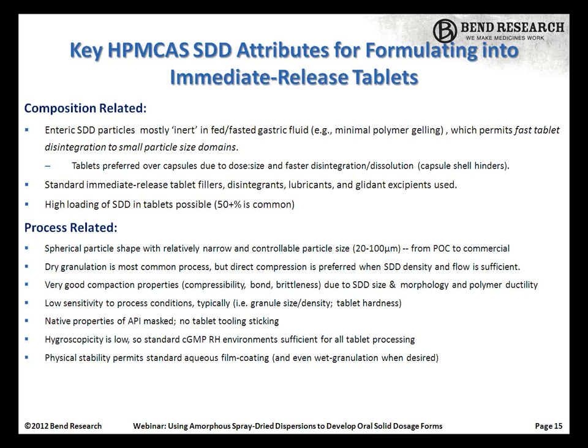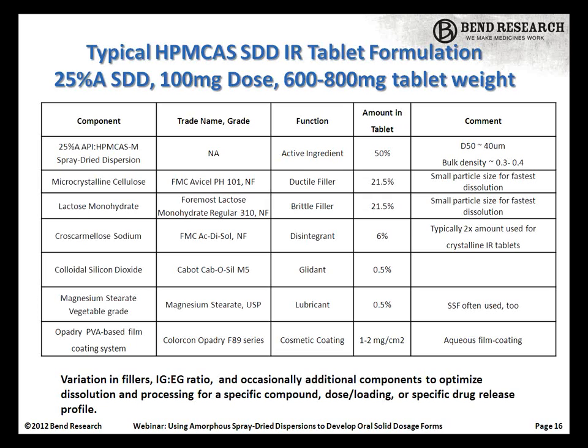On this slide here, I've shown what would be sort of a black box formulation that works for an awful lot of SDDs. There are some subtleties to this, but if you just look at the composition and the amounts, you'll see again they're quite similar to what you do for conventional API. I'll just go through the comments here. So the ranges in the tablet, I mentioned the ranges are maybe 70% and below, and certainly 50% is common.